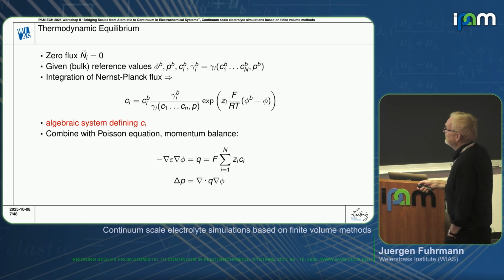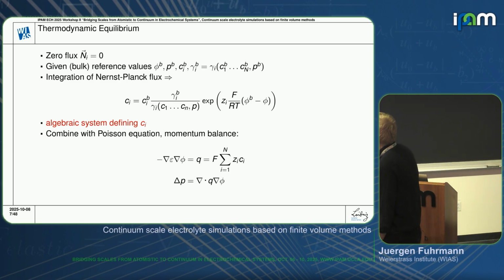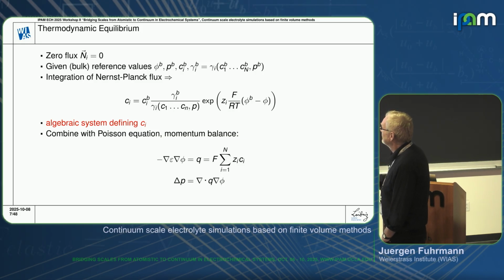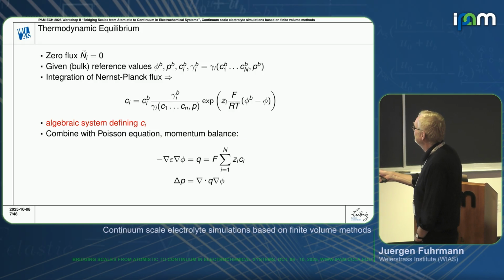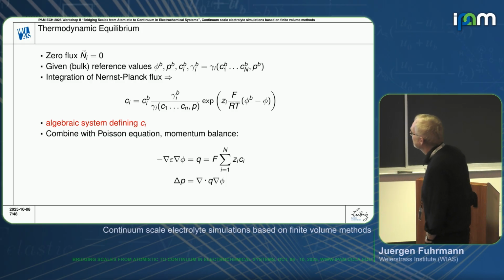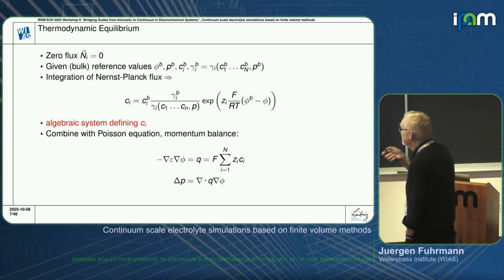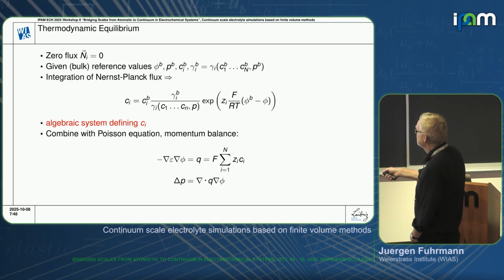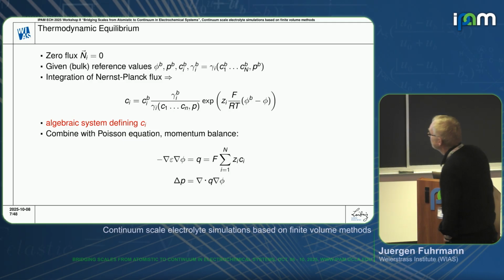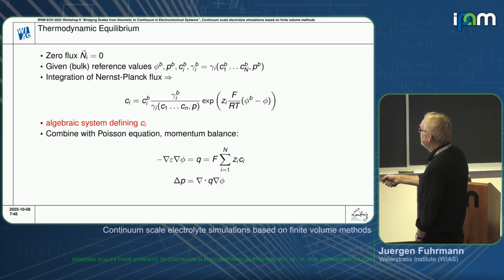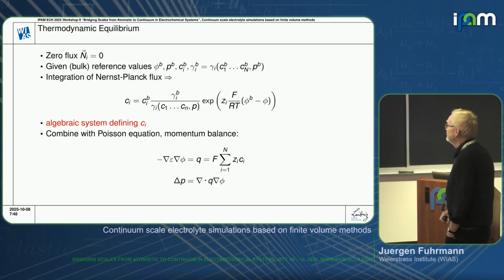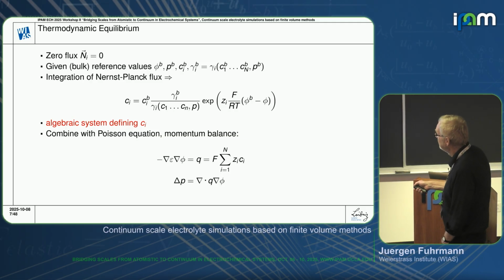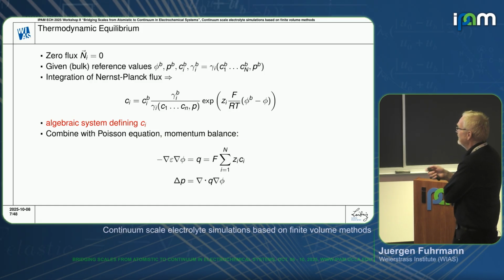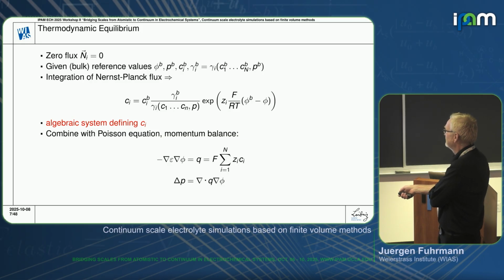Okay, so if you look at the thermodynamic equilibrium, we basically can integrate the Nernst-Planck fluxes. We set them to 0, give bulk reference values for concentrations, potentials and pressure, which then also give rise to the bulk values of the activity coefficients. And then we can, for instance, have this expression for the concentrations, which is an algebraic system which couples all the concentrations, if we write it in this way. And we can combine this with the Poisson equation and the momentum balance.